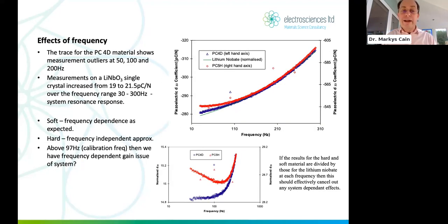Frequency. So I'm going to rattle through these now a little bit quicker because I've got the basic physics underway already. So what about frequency? Now, when we measure at different frequencies, we'd say at 97 hertz we do most of our experiments. What happens if we do it at twice that frequency, or 3 times, or 50 or 40 hertz, or something like this? Well, if you have a lithium niobate material, which is a nice linear, stable source-ish, then you can measure that as a function of frequency